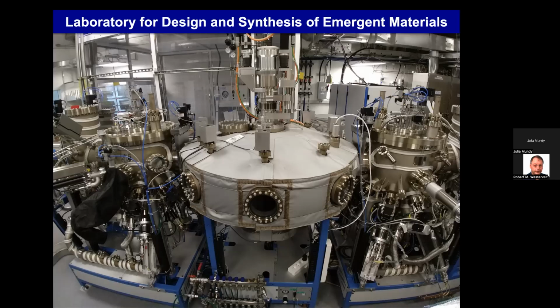So if we want to grow a really thick film, we might have to wait 8 to 12 hours. That's why we want things to be super stable. We do have some projects, with Marco Longchart for example, for photonic devices. They want to couple light in, so it has to be about a wavelength of light, a micron. So there are applications where we care that we can make it thicker. But for most cases, is it magnetic, superconducting, a ferromagnet, whatever, you're going to make it smaller. They're still very small amounts, micrograms of material. If you hold a sample in your hand, most of it is just the substrate, with a very thin coating on it.